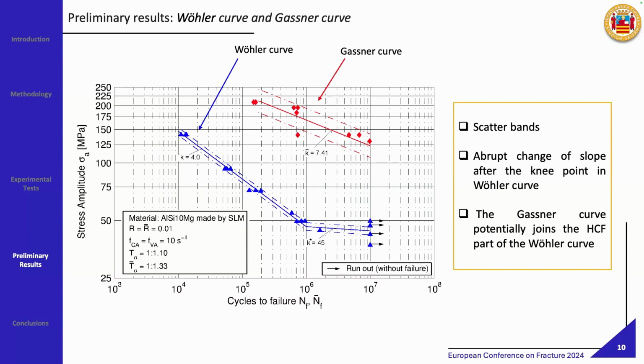Concerning the Gassner curve, what we can say is that each point, first of all, is positioned on the plot considering the stress amplitude, which is relative to the maximum stress of the considered loading spectrum. In this case, results are a bit more scattered. We can see how the slope is less steep compared to the Wöhler curve. So at least at this stage, it seems that the material is, let's say, less sensitive to this kind of loading. And we can assume that the Gassner curve or its eventual knee point potentially joins the Wöhler curve towards the high cycle fatigue part.